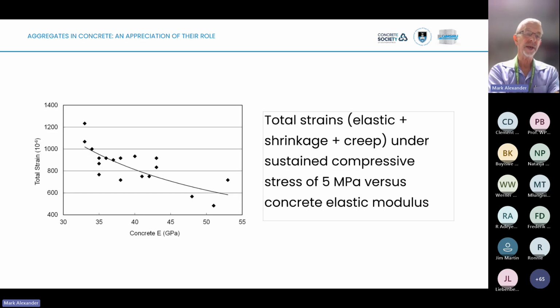And this is the one, again, the restraint effect. If you plot total strain, which would be elastic plus shrinkage plus creep, under sustained compressive stress here of 5 megapascal versus the elastic modulus. Okay, there's a lot of scatter on this graph, but the general feeling or the general trend is there. Higher concrete elastic modulus, lower total strains.